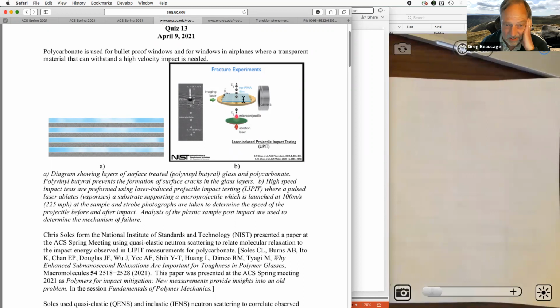So it turns out polycarbonate is a great material for this. It's got a huge energy absorption when this particle flies through it. For that reason, it's used in bulletproof glass. So you have layers of glass and layers of polycarbonate, and glass becomes brittle because of surface flaws. If you coat the surface with this polyvinyl butyral polymer, it'll deactivate the surface, so it's harder for cracks to initiate at the surface, making the glass like super glass. And then the polycarbonate. It turns out 2 layers of polycarbonate can absorb like 10 times as much as one layer that's twice as thick. So the more layers you have, the better.